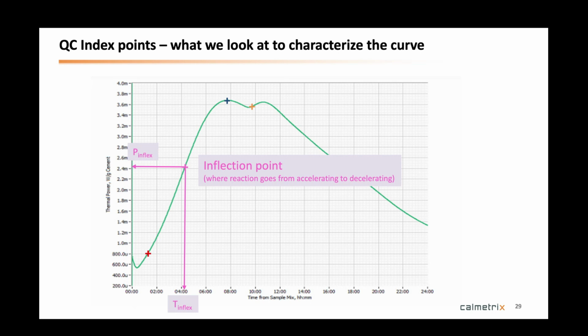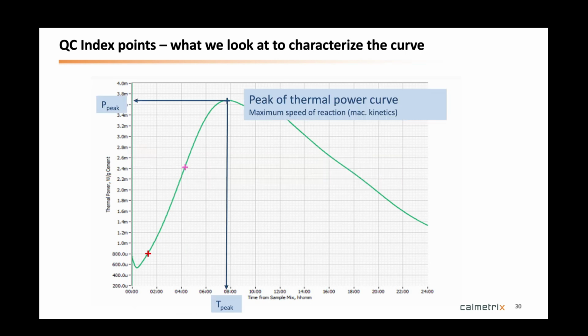And then the next one is the peak of the thermal power curve. And that one is interesting because that's the maximum speed of reaction. This is a speed curve, remember, it's instantaneous speed. So this is really where the molecules in there are the most active and the fastest in combining before they gradually do it slower and slower. But this is really the peak value of the speed, and you do want to know at what time that happens and what the highest power is. If the power is very high, it means higher speed, so very reactive mix. And if this occurs very early, then it's a very fast mix in general, in terms of everything. Every performance parameter will happen faster.